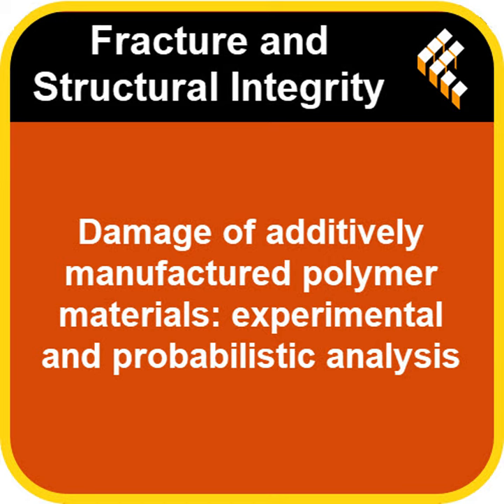So to quickly sum up this deep dive for you listening, print orientation. It's absolutely fundamental to the strength of your 3D printed polymer parts. Don't ignore it. Cannot stress that enough. Second, any crack, even a tiny one, matters. There doesn't seem to be a magical safe size below which it has zero effect. It always weakens the material somewhat. Gradual weakening, but it's there. Damage progresses through predictable stages as a crack grows relative to the part size, becoming uncontrollably unstable after hitting a critical threshold, which this study found to be around 50% of the width, or a life fraction of 0.5. That 0.5 mark seems really key.